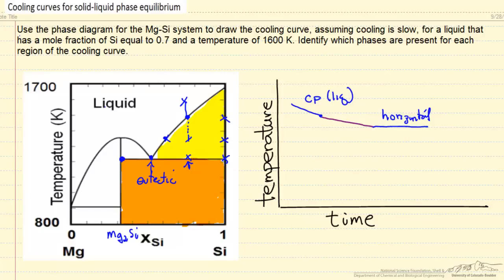When we continue to remove energy, we move down to this point, which has this composition of pure silicon and this composition of the compound. The only thing we're changing is that we're lowering the temperature. We have no further phase change, so now we're looking at changes due to heat capacity. The heat capacity of the solid determines the slope of this line.